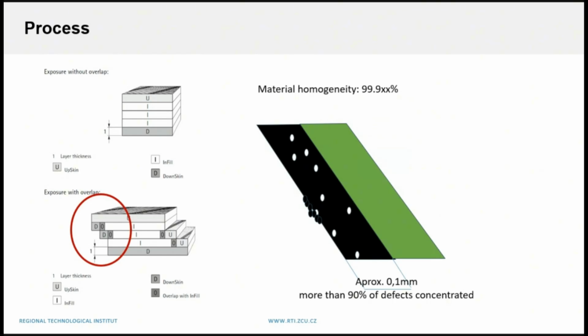Generally, we can say that the homogeneity of the printed materials is more than 99.9%. And in these few percent, the mistakes of the materials are concentrated generally in areas where we use downskins and overlapping of the infill. Here are concentrated pores and lack of fusion, and with the angles, the roughness of the bottom surface increases very quickly. So in the area of fatigue life, it is very problematic.